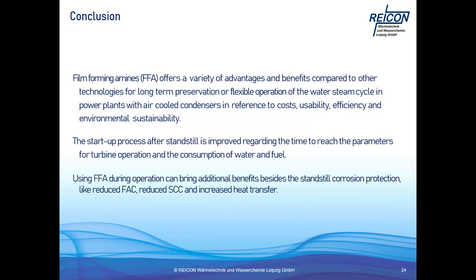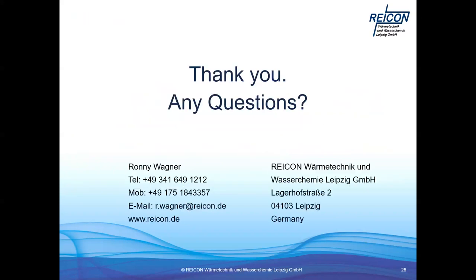And as I said already, the application can have additional benefits like reduced FAC, reduced stress corrosion cracking, and also an increased heat transfer by removal of these porous oxide layers in the system. So thanks everyone for watching, and if there are any questions, please let me know.